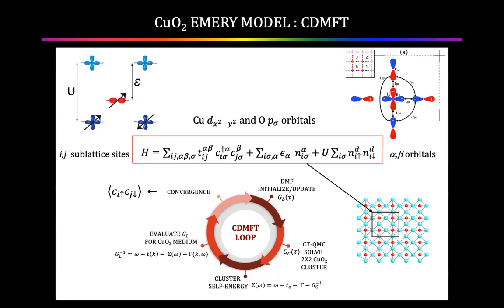And now you could say, okay, if it's superconducting, tell me what is the mechanism? I didn't see the hypothesis for the mechanism going into this story, but it is there. The hypothesis just has to do with the hopping rates having to do with the charge transfer energy, which is allowing hopping of holes on and off of the oxygen sites. That's it. And in modern versions of this theory, as they adjust the charge transfer rate, it controls the strength of the superconductivity. So you could parameterize this as super exchange energy by this charge transfer rate, but the super exchange doesn't appear explicitly in the Hamiltonian. What appears in the Hamiltonian is the difference in energy between the p orbital and the d orbital. So charge transfer super exchange is the mechanism in this calculation.